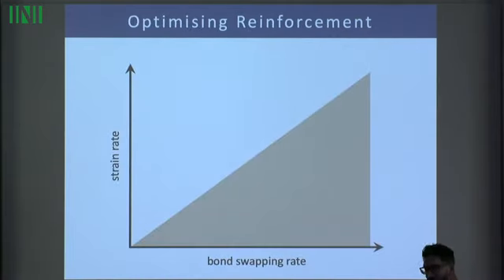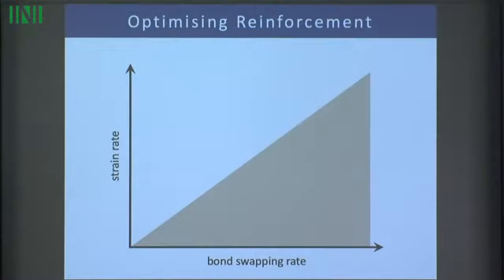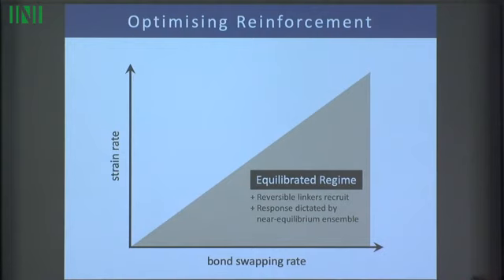But the story is a bit more complex because now we have to think about the kinetics of this, because if the linkers are very weak binding, they might recruit, but they might not stay long enough to actually bear any load that's usable for the material. And so we can draw this rough schematic where we look at the strain rate of the material on the vertical axis and the bond swapping rate on the horizontal axis, and we can divide it into two regimes. Over here, if the swapping rate is very fast, but the strain rate is very slow, you can kind of call that the equilibrated regime, and that's where actually we're straining very slowly, and so the reversible links are moving around very quickly. And so the responsive material will be quite dictated by the equilibrium ensemble, which is this clustered ensemble of reversible crosslinks.